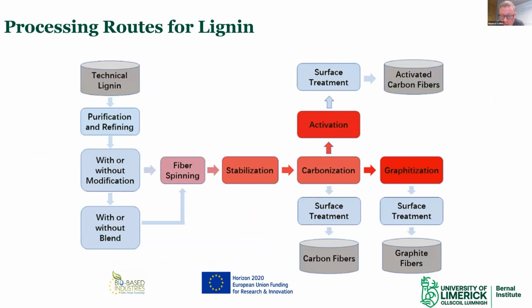So this was the processing route. We get technical lignin as the waste from the paper making industry, and we purify it and we refine that technical lignin. And then we can modify it. Sometimes we chemically modify it, sometimes we don't. We just use it as is, and then we blend it with another biopolymer. We tried various biopolymers. I'll talk to you about those in a while. We spun those blends into fibers. Then we stabilize them before we convert it to carbon, because you have to stabilize. If you don't, it'll just melt. So that involved some nice novel cross-linking regimes that were able to cross-link the fiber as we heated it up. Then we heated it to over 1,000 degrees C, carbonized it, did some surface treatment before deploying it in a composite.